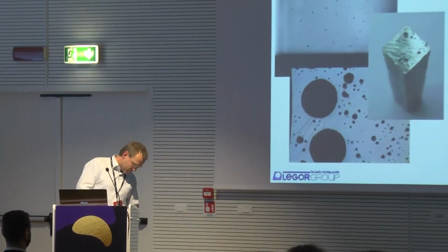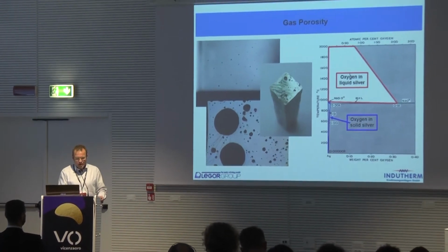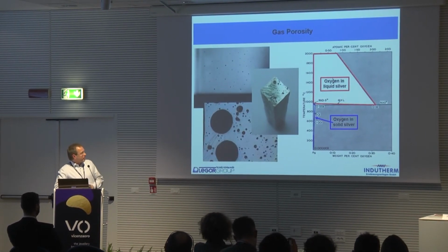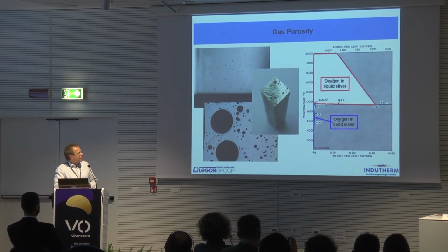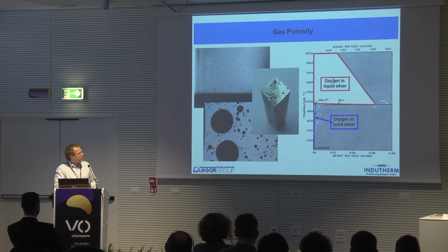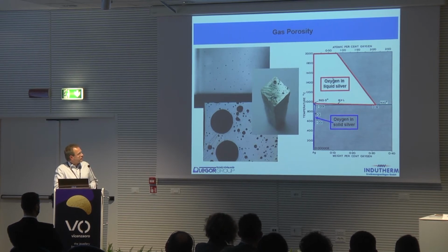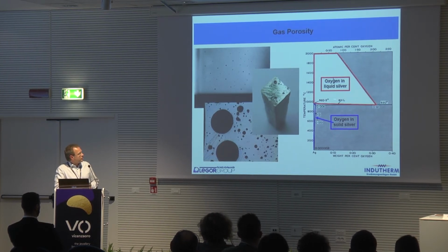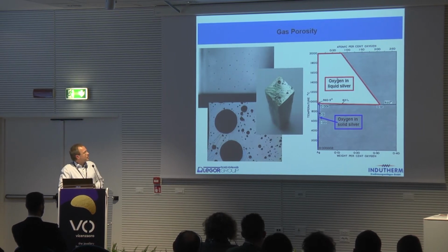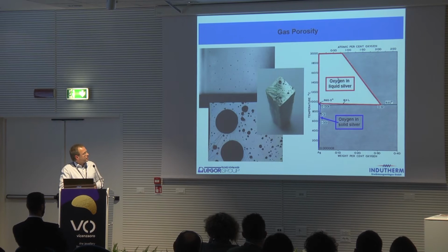We're already coming to the second type of porosity that I want to talk about, namely gas porosity. Again, sterling silver is a good example here because it's very prone to gas porosity. Why? Like all molten metals, you can dissolve a lot of oxygen in the molten metal at high temperatures. This is indicated by this diagram where you can see the amount of dissolved oxygen as a function of temperature. In this part here, we are above the liquidus temperature of pure silver, and this area indicates the amount of oxygen that we can dissolve in the molten metal.